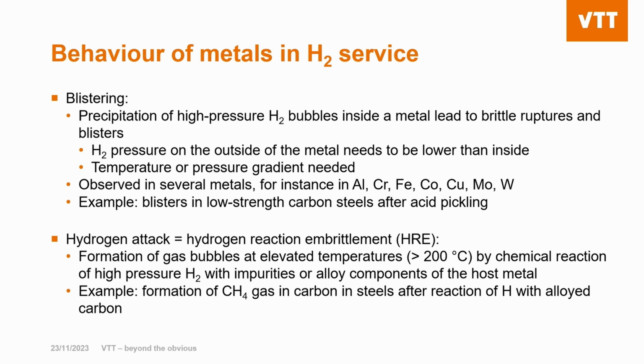Another phenomenon is hydrogen attack or hydrogen reaction embrittlement. That usually takes place at higher temperatures. Here the hydrogen reacts chemically with the carbon in the steel, for instance. It can also react with oxygen in copper, and then water would form. For instance, when we have carbon in steel, methane forms.